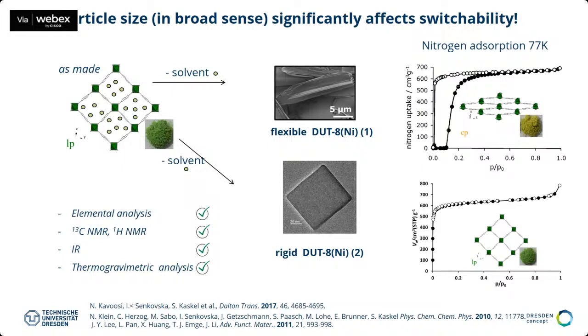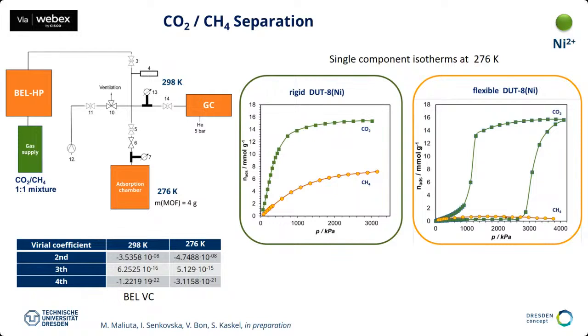This gives you also another way to tailor the properties of these kind of materials, but it's very important to keep this in mind, because when you tailor the cluster, you always need to compare also similar crystallite size, and this is another dimension to tailor the properties of these systems. And this is very important for the selective separation of gases. For example, CO2 separation is an important topic for environmental applications, and also the separation of CO2 from methane is an important industrial separation. When you want to basically have a pure natural gas, you want to have an adsorbent which selectively takes up the CO2.